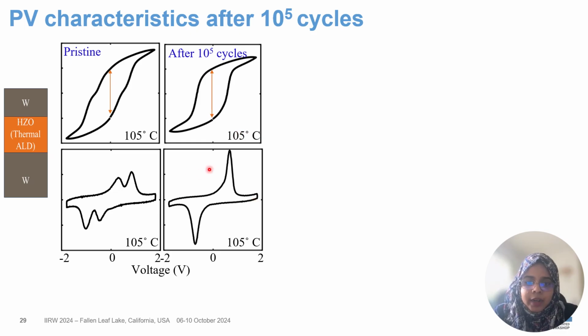So what we saw is that after 10^5 cycles, these are the curves coming from 105 degrees Celsius, and what we are seeing is that at pristine state we were having a pinched loop, we were having a double peak in our current, but after 10^5 cycles we are able to get a proper ferroelectric loop, and also we could remove the double hysteresis in our current. So this tells us that 10^5 cycles are necessary to wake these devices which are thermal ALD deposited.